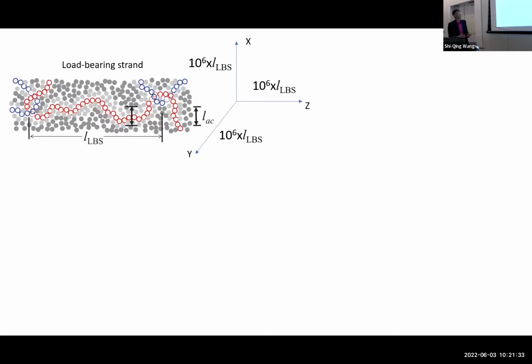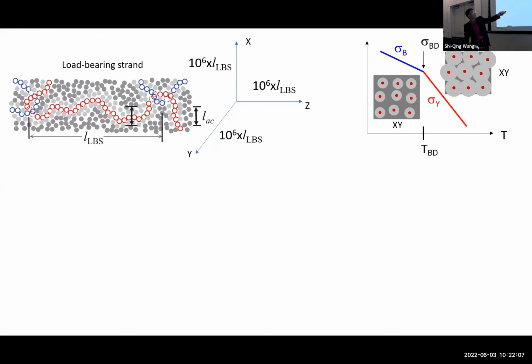So the picture for us to proceed to understand why some glassy polymer can be ductile is these load-bearing strands I stretch globally. Keep in mind, my sample will involve millions of such units. But these load-bearing strands, as I stretch from one end to the other end, 1 million away, they will start to be displaced. When they get displaced, the neighbor will eventually start to move around. So you can create some activation zones, if you like. And that grows as you stretch more and more. So the brittle-ductile transition, in my mind, was a Goldilocks temperature above which the network survives and activates, below which the network falls apart, and therefore, of course, you cannot achieve activation. And there's no mobility available for you to match with the imposed rate.